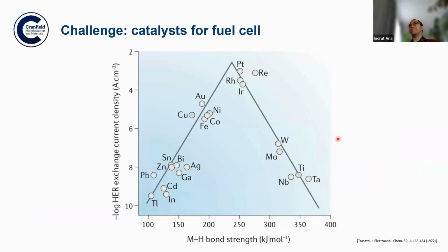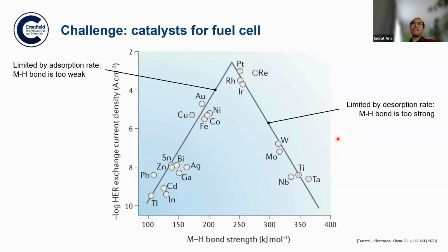This is a volcano diagram of catalysis. If you have learned a little bit of chemistry, you perhaps have seen this volcano diagram. On the y-axis, this is the hydrogen evolution reaction activity. On the x-axis, this is the bond strength between the metal and the hydrogen. On the left-hand side, this is the limit of adsorption, so all the materials there have a weak metal-to-hydrogen bond. On the right-hand side, you have a strong metal-to-hydrogen bond. A good catalyst will sit at the center, a balance between adsorption and desorption. You don't want it to adsorb too strongly or desorb too strongly.